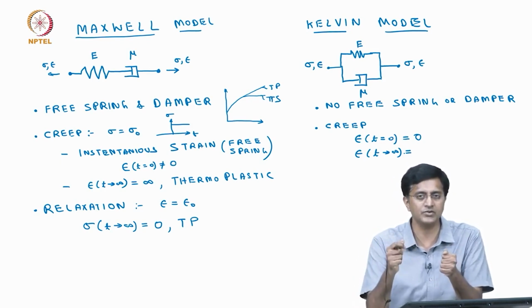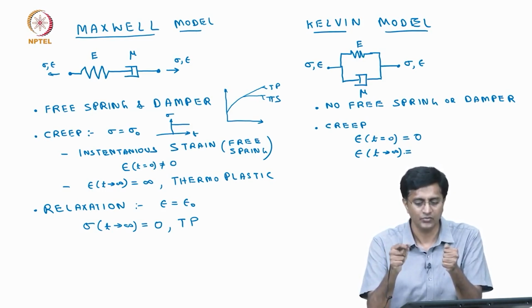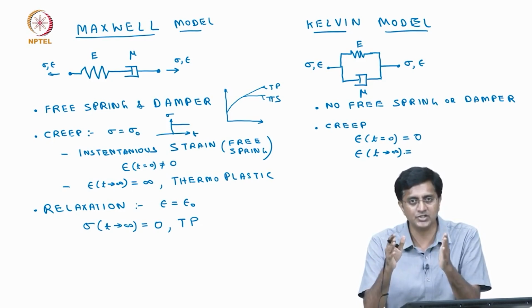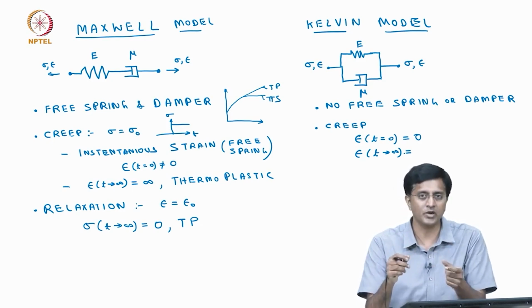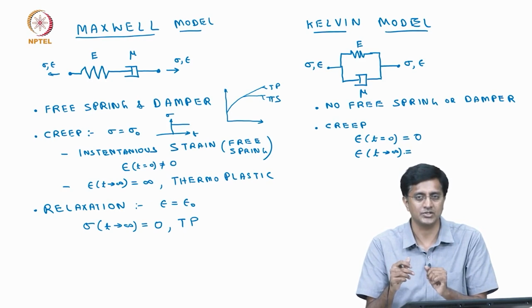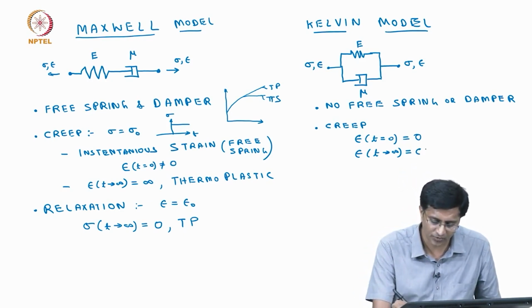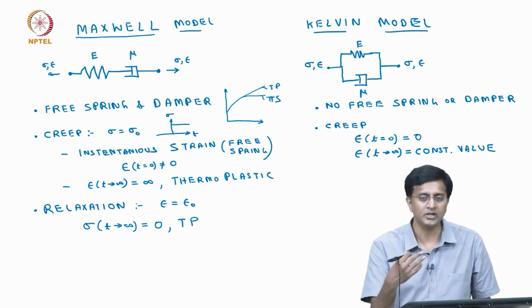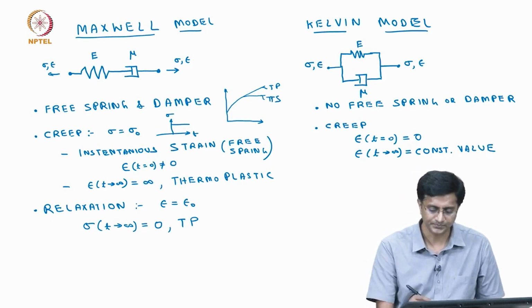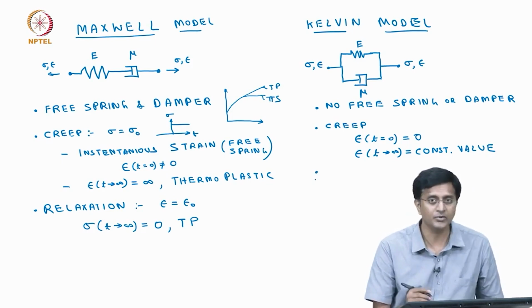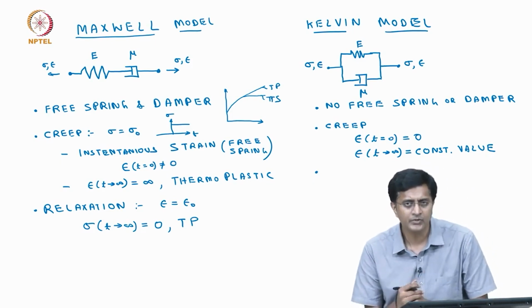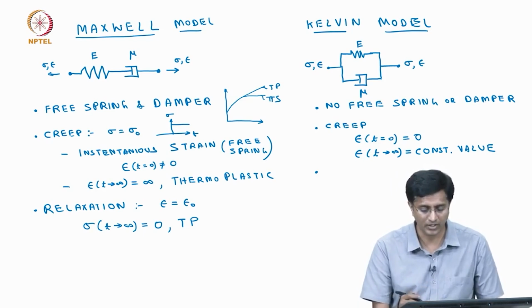load, right? The kind of test we are doing is we applied a fixed load, which means the deformation increases until the spring is stretched to the corresponding amount of strain, and then it remains constant. So, if we wait for long times, it reaches a constant value, and this constant value depends on the spring and not on the damper. Okay. Now, let us come to a very interesting experiment or an observation we will have.